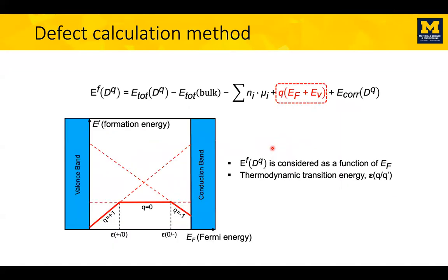And when you put this all together, you get plots like this, okay? Your formation energy on the y-axis depends on the Fermi level. The neutral defect doesn't depend on the Fermi level. That's why you see this constant value here. A positively charged defect increases with Fermi level and the negative decreases. So for any given Fermi level, we're trying to find the most stable state of the defect. If your Fermi level is close to the valence band, that means your defect would rather give electrons to the Fermi level, which is low, and reduce its energy. As you increase the Fermi level, though, eventually the defect will be neutral. And if you increase it and get close to the conduction band, then electrons would leave the Fermi level and go to your defect and charge it negatively. Okay, so that's what you will see here.